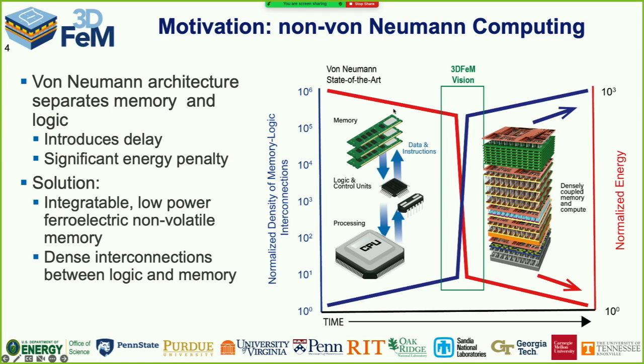If we could move to a scenario where instead of having that memory be distinct, it was integrated directly on top of the processor, now you should be able to make a step change in the memory logic interconnections. And if you could do that, you should be able to remove a substantial fraction of the energy burden. Depending on whose numbers you read, it could be up to a 1,000-fold reduction in the power associated with computation. That's not trivial. And it should substantially reduce latency. So let's imagine that this sounds like a good thing. How would we go about doing that?